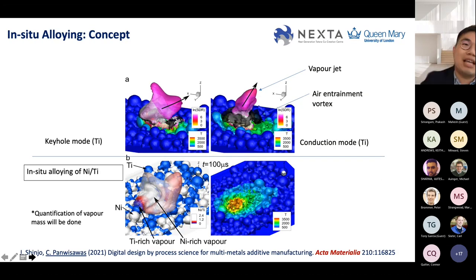So once we understand the elemental behavior, we want to mix them together now. The challenge is quite high because we have a lot of things we don't know, for example, interaction terms and interfacial energy, but we want to use some kind of traditional rule of mixture assumption to go further to get to the in-situ alloying of these two materials. For example, in this system, we have a nickel-titanium alloy where you can quantify the vapor mass or mass loss as a function of a process parameter. And this is a very important step for us to understand how things mix together. That's why the title is called species mixing. So this is the concept.